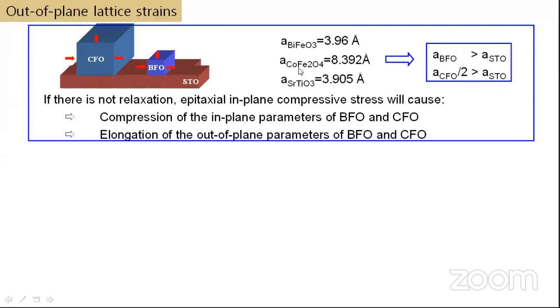Similarly, the lattice parameter of cobalt ferrite is 8.3. So if you take two unit cells of perovskite strontium titanate, the cobalt ferrite lattice parameter will be larger than two unit cells of strontium titanate. Again, what will happen is you will have in-plane compression and out-of-plane expansion here.